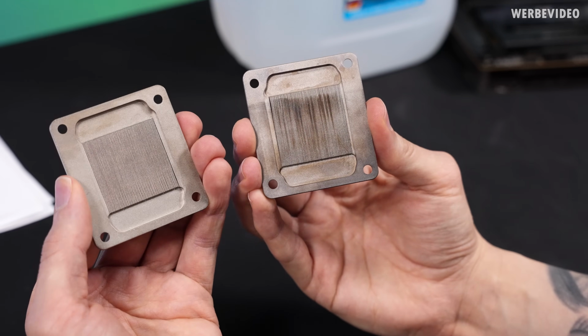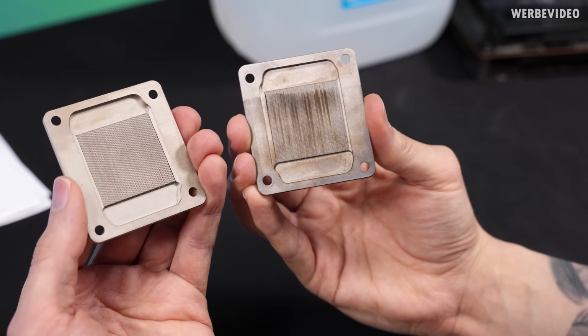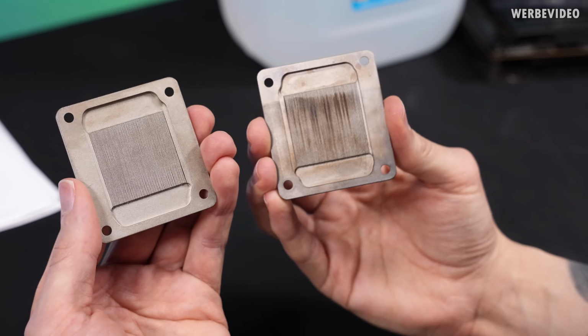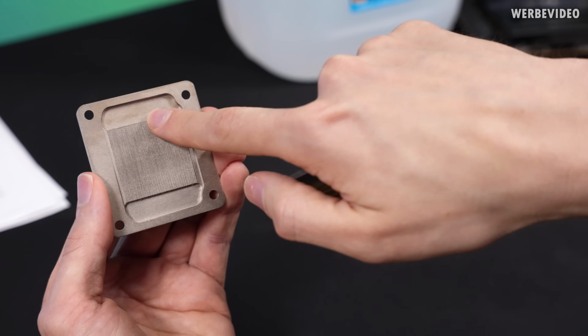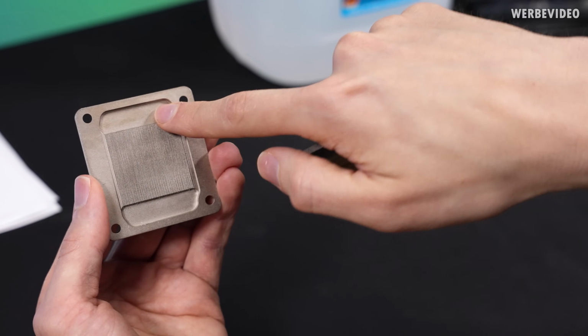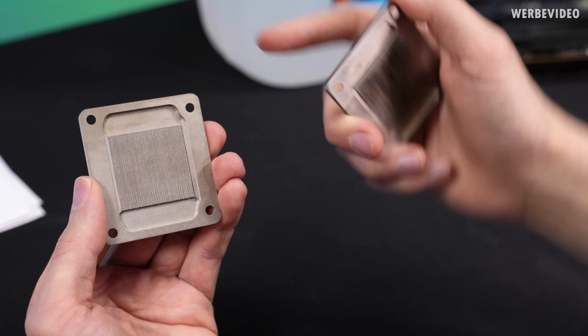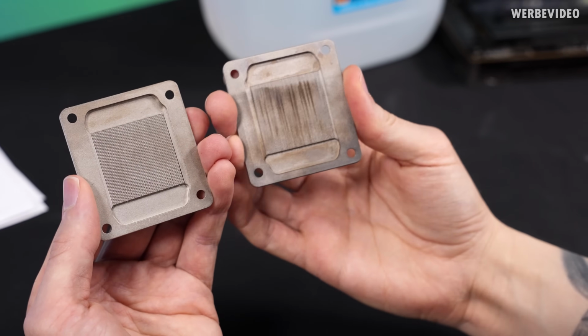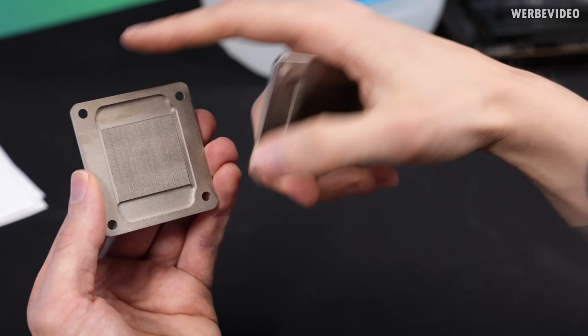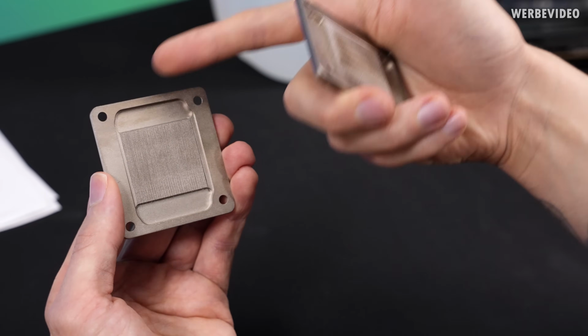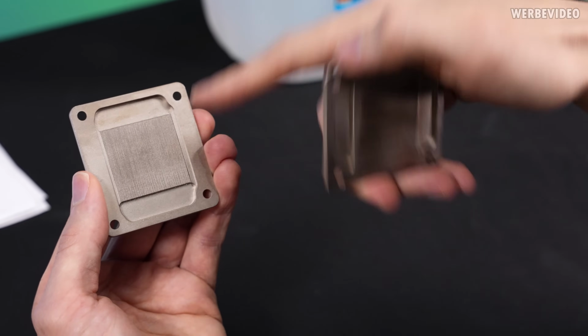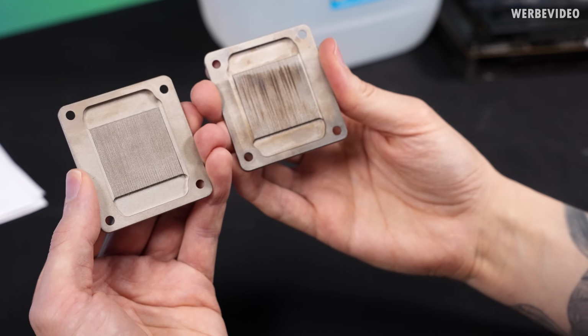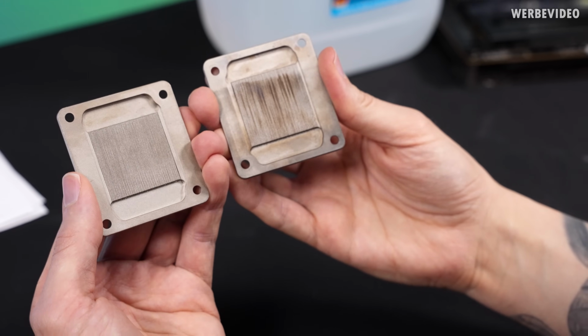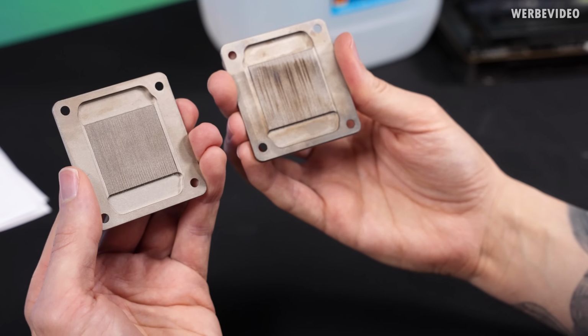And on the left side, we have the one that was submerged in the DP Ultra for three times as long. Again, you can see the line where the water was at. So everything outside, it's kind of expected that you will see some kind of discoloration simply because it's also exposed to oxygen, but this is still fine. But everything that was fully submerged in the DP Ultra, there is no corrosion at all. There's nothing visible, even though this was used three times as long as this one.